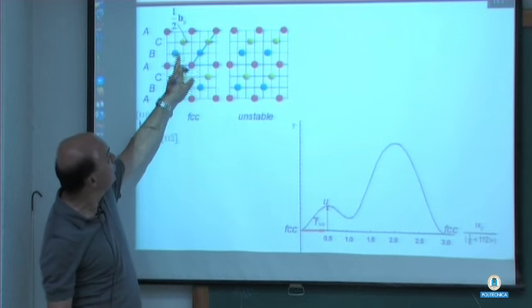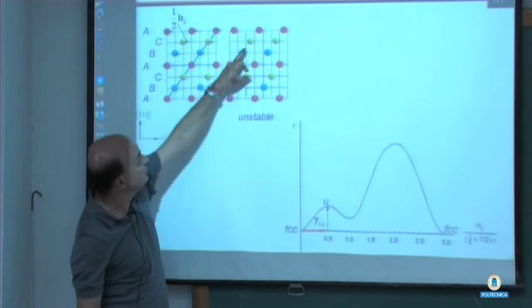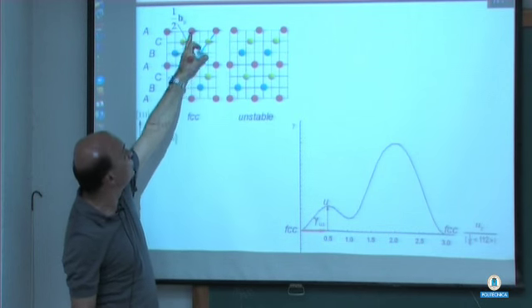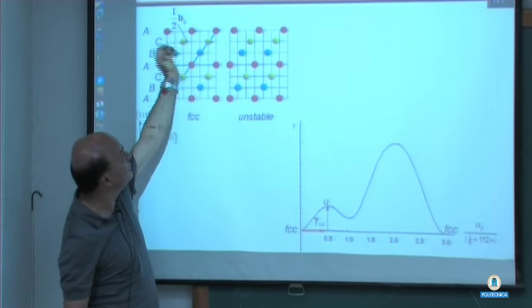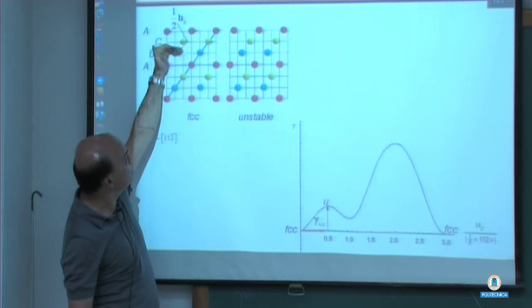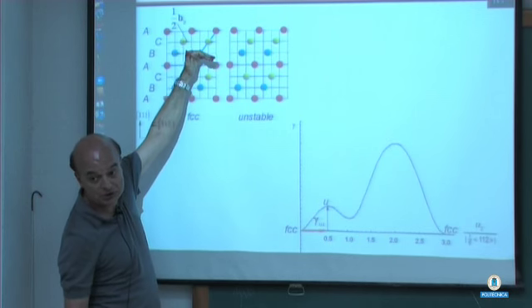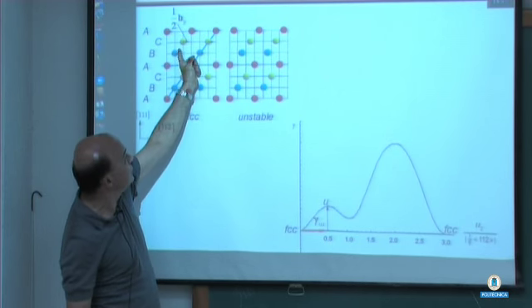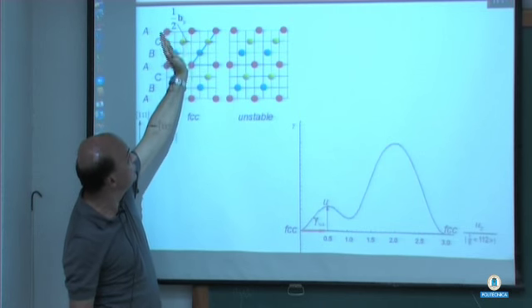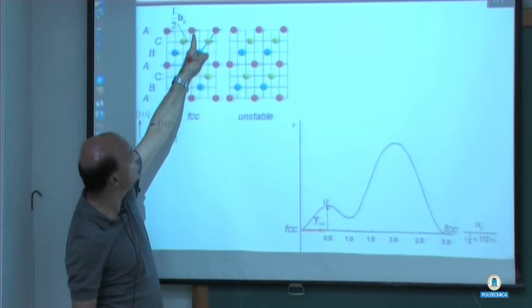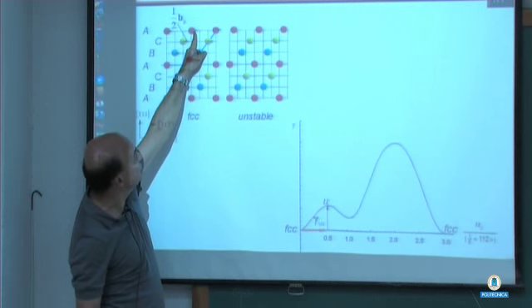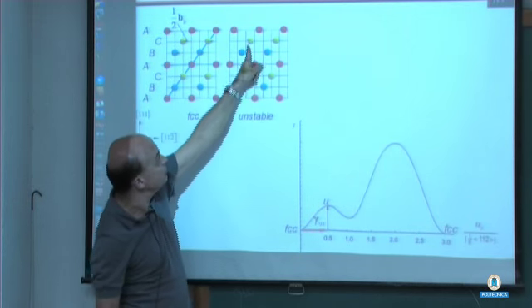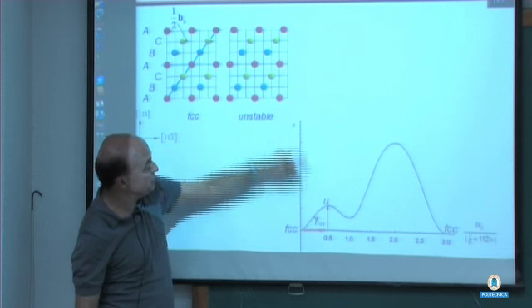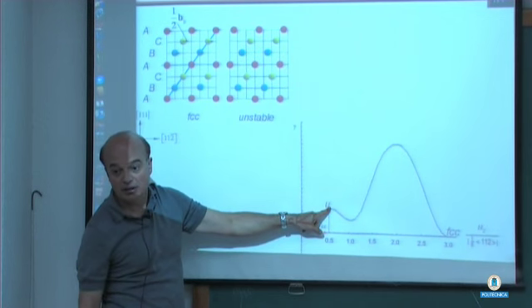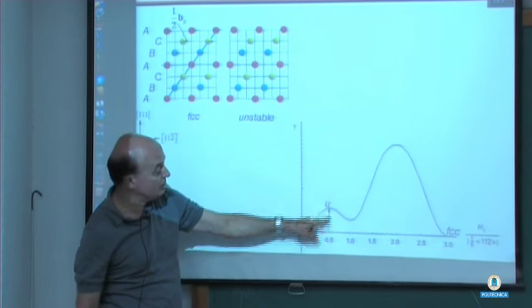So that would be when the blue is right in the middle here, the green is right in the middle there, okay, and you move everything on top here. I'm trying to push a partial dislocation through, but this is not quite the entire partial dislocation motion yet. So here this moves here again, so you get this configuration, which corresponds to a highly energetically unfavorable state.